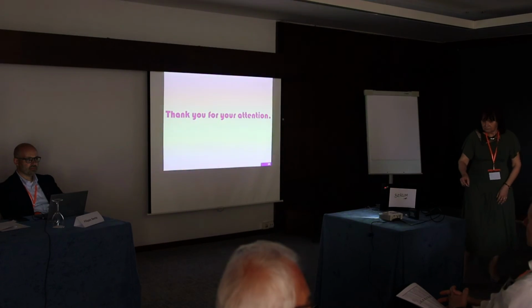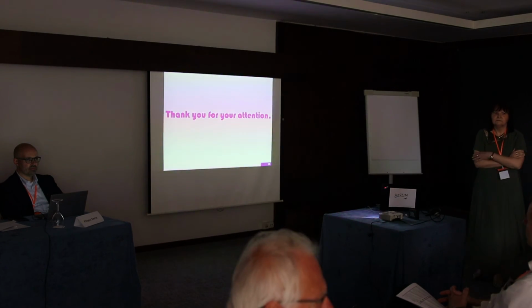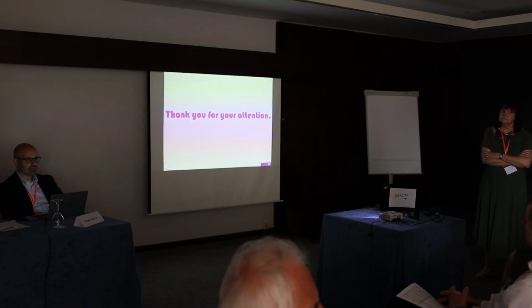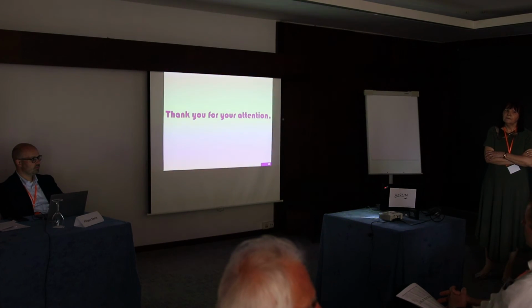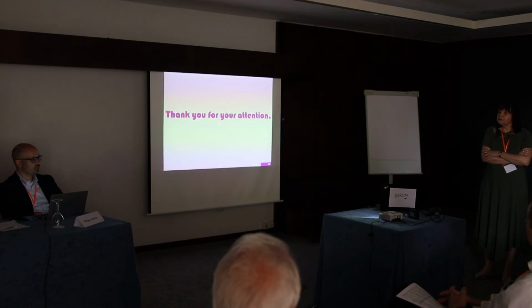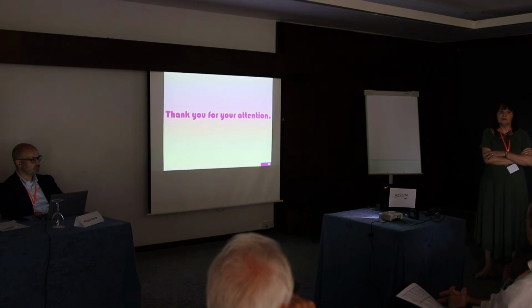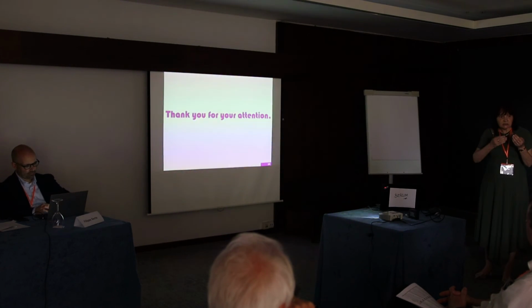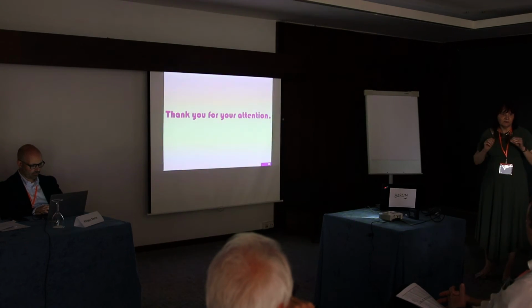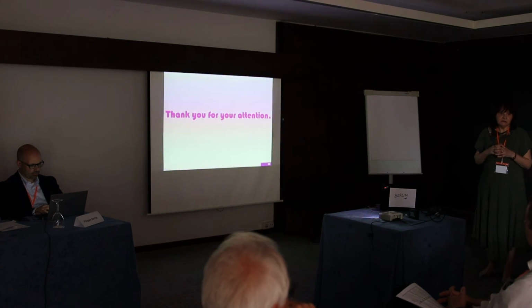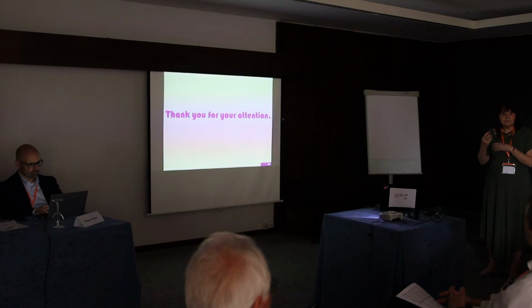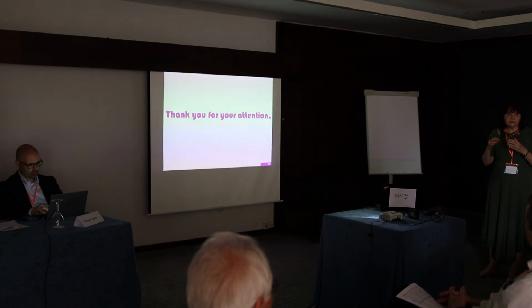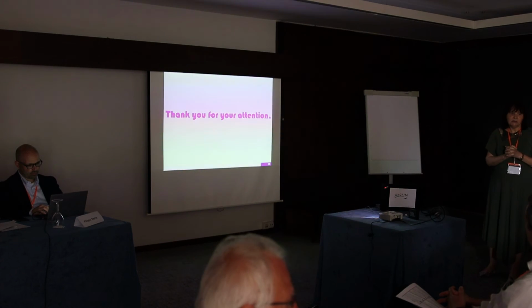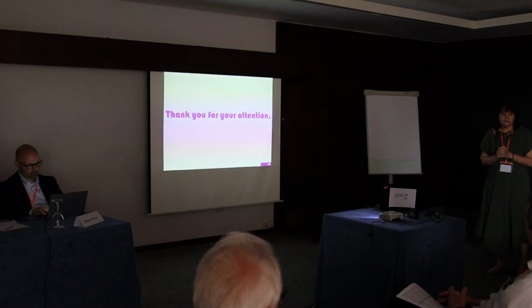Yes, please. Thank you. Have you done any study on the microstructural defects related to the poor surface quality on the walls? In this study, it's interesting only the roughness of the surface, in this case, the surface on the bottom of the notch. So defects don't play a role because there are not many. So this is technology which was improved in this company.